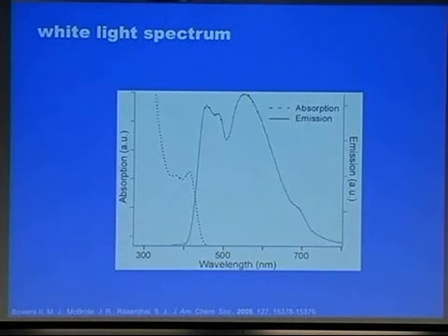So this is the last spectrum that I'll show. Here's 400 nanometers, and here's 700 nanometers. Remember before I showed you all those different sizes that gave peaks going from 400 to 700. Well, these little baby nanocrystals emit the entire visible spectrum. And it's almost as if it was done by intelligent design. It starts at 400 nanometers, which is where your eye turns on, and it stops at 700 nanometers where your eye turns off.